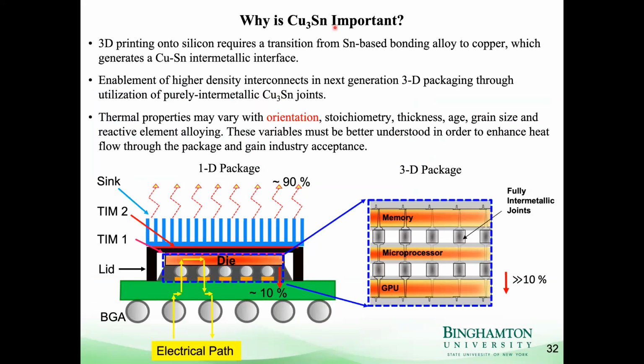So Cu3Sn, as I mentioned, is going to be present when we print this tin, silver, titanium alloy onto silicon and then print copper on top of it. But it's also important for other applications. So all of our cell phones, I don't know where mine is at the moment, and our computers have Cu3Sn inside of them. So solders contain Cu3Sn. And next generation integration schemes may be made purely of Cu3Sn intermetallic bonds. So there's going to be 3D stacking of chips. And one of the things that's anticipated is that pure copper tin intermetallic joints may be formed. In that case, Cu3Sn will be a rather thick layer.